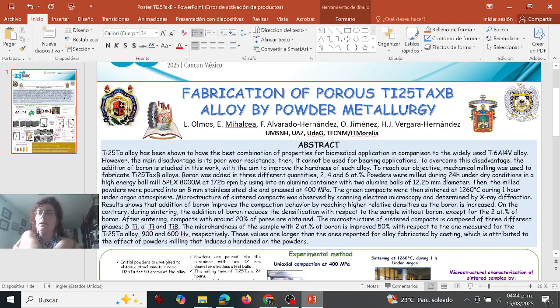So the microhardness of the samples with 2% of boron was improved by 50% with respect to the one measured for the titanium 25 tantalum alloy, and for 900 and 600 HV respectively. So those values are larger than the ones reported for alloy fabricated by casting, for example, which is attributed to the effect of the powder milling that induces a hardening of the powders.